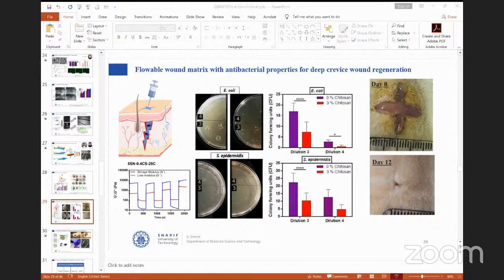So the doctor can inject the hydrogel on the injured surfaces by a nozzle or by a syringe. And the important point is the behavior of the gel is reversible. So during injection it is a fluid, after injection it is a stiff body. We incorporated chitosan nanoparticles and drug inside our gels. Chitosan is important because it can bring antibacterial effect and also encapsulate the drug inside.